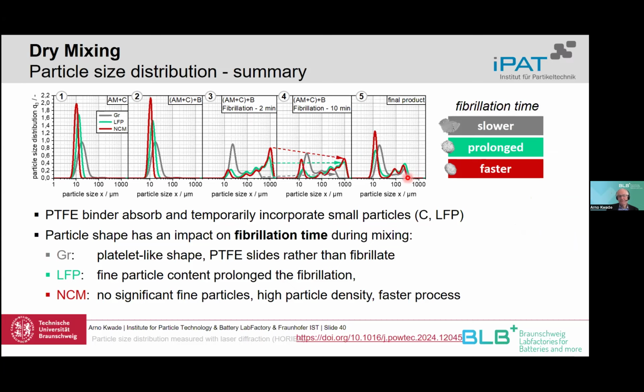So for the NMC, it's the same. It was very similar to the LFP. And you see that with the graphite, the PTFE slides more than it fibrillates, because graphite has a really low friction. And for LFP, there's a fine particle content, which is still there also after fibrillation. And we have a fast process here also for the NMC.